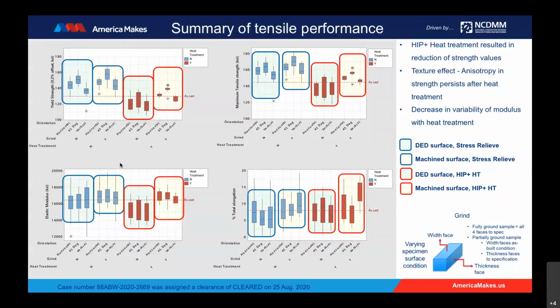So here on this slide we have a summary of the mechanical testing data, where data from all the different process conditions was pulled together, and then we segmented by test orientation, meaning the gauge orientation with respect to horizontal during the tensile test, and surface condition. So here we've looked at specimens with as-built surface condition on 2 faces of the gauge volume and fully ground surface finish on all 4 faces of the gauge volume. So these were flat dog bone tensile coupons, and then the heat treatment effect. So in the as-built and stress relieved, and then HIP and aged.